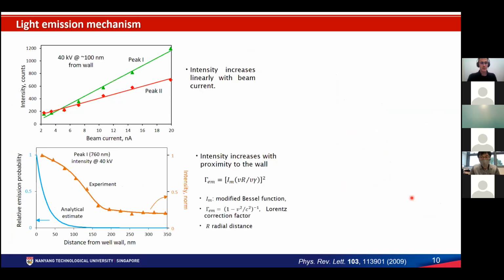We further characterize the well. We increase the intensity to see what kind of emission regime we are in. It looks like we're still in the linear regime up to a beam current of a few nanoamperes. We also see how the emission evolves as we approach the well from the center to the distance. You can see that from a zero or flat emission when you're close to the center, you start feeling the dielectric environment when you approach about 150 to 100 nanometers away from the well.